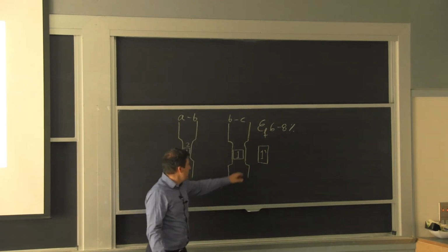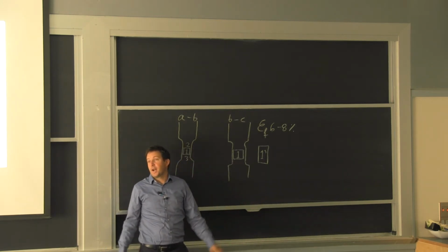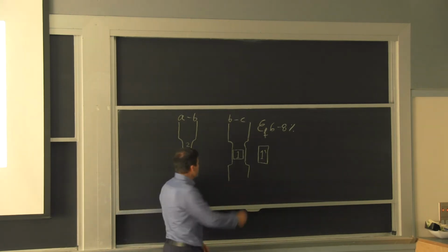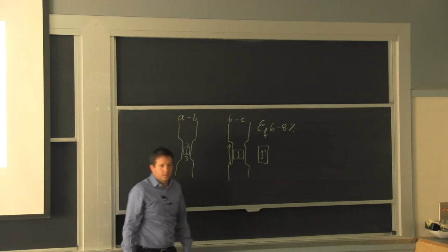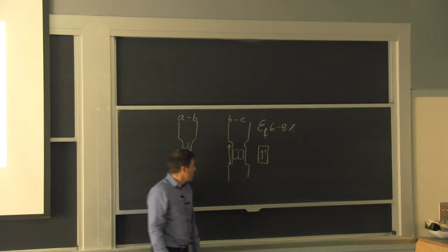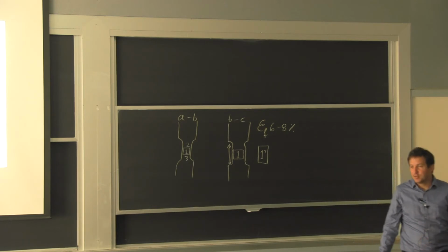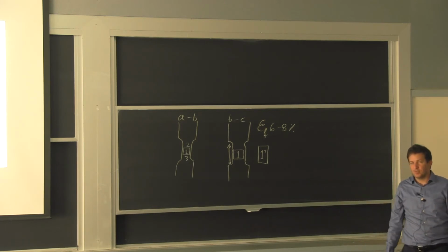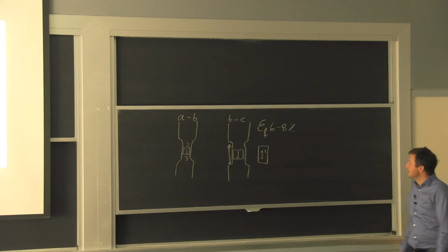In reality, in that zone the actual strain is much higher. It's just because we were making our reference with respect to the whole cross section when we calculate that strain level. Keep it in mind, please, because I've had to correct too many people on this, practicing engineers with engineering licenses and a lot of credentials, a lot that you would think you could trust.